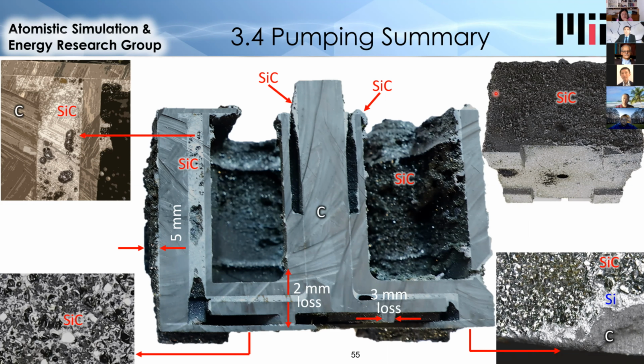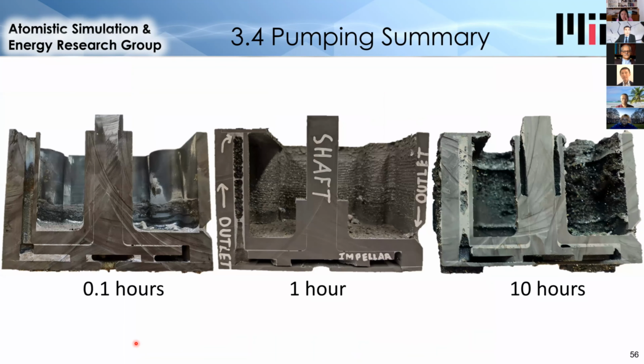And we can see silicon carbide deposition all over the inside and the outside of the pump, with most of it at the top of the pump where it was colder. And so this is just another indication of the problem of dissolution because of the high solubility of carbon in silicon. Another way to view this is the 3 experiments shown next to each other, which shows the degradation over time. So in the short 0.1 hour experiment, we don't see much silicon carbide deposition. In the 1 hour experiment, we see that the outlet is partially clogged, and then finally, after 10 hours, it's